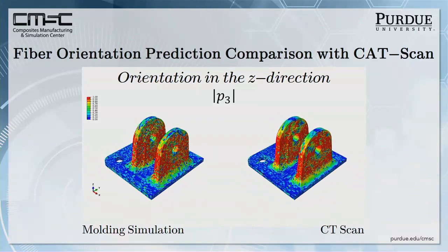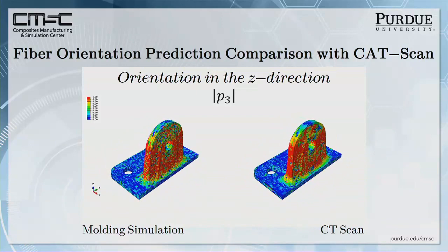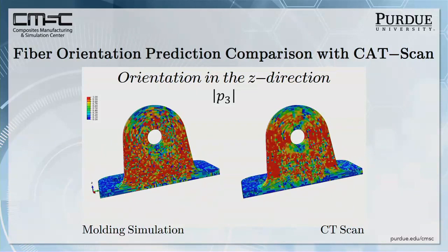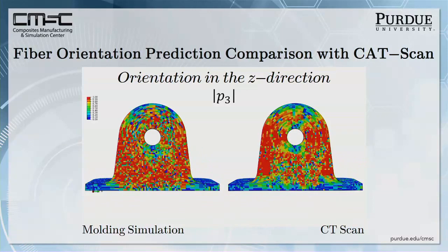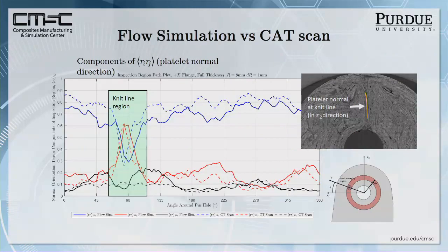And the answer is on the left is the molding simulation, and on the right is the CAT scan. So we've CAT scanned these and reassembled the CAT scan and compared the two. And when you look at that, you say, well, those sure look alike. Well, let's do one experiment, which is to run around the circle a little and sweep out an area and then plot the components of the orientation tensor and see how our predictions and our plots of the actual measurements look.